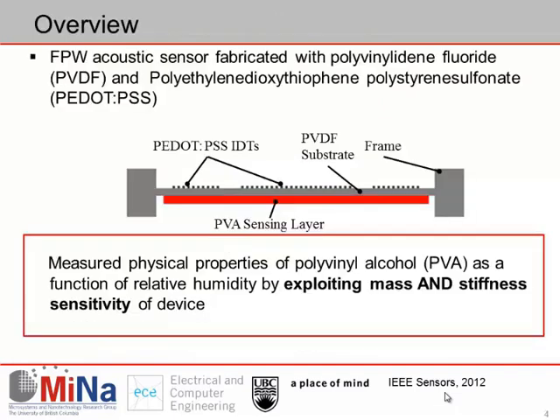So what we've done is we've fabricated a flexural plate wave sensor out of polyvinylidene fluoride as the piezoelectric substrate and polyethylene dioxythiophene polystyrene sulfonate as the interdigitated transducers, so both polymers. We then used this sensor, pictured in cross-section here, to measure the physical properties of a drop-cast polyvinyl alcohol sensing layer. Specifically, we did this by exploiting both mass and stiffness sensitivity of the device. This is exciting, as I just mentioned previously, because most FPW and SAW sensors exploit only gravimetric sensing.